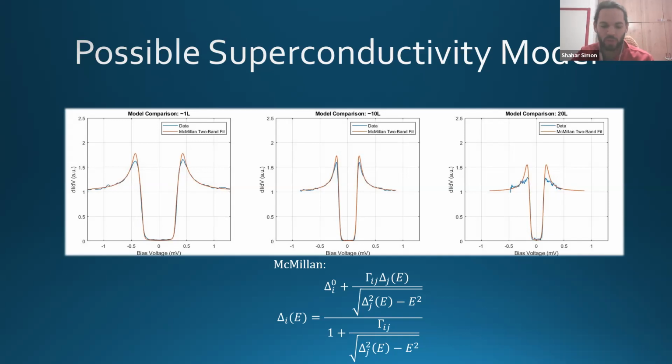So at this point, we believe that the material is BCS or BCS-like. And what we're seeing here in this diminishing of the quasi-particle peaks is just chemistry of degradation, of being exposed to air, and not real physics of the superconducting order parameter. So right now, we believe that this material is BCS-like, but it does have this interesting behavior of getting larger and larger deltas as you thin it down.